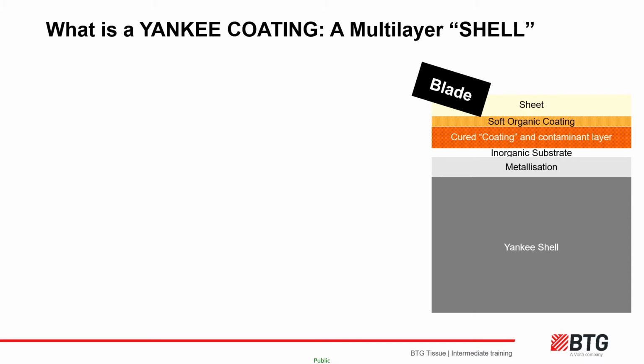If we could take a cross section through what would be an ideal Yankee coating, these are the layers we would want to see. On top of the Yankee shell and any metallization layer would be an inorganic substrate made up of minerals and salts, either naturally there from the spray or process water source. These would be calcium carbonate, iron and magnesium salts. They could also be deliberately placed there, for example by phosphate addition, and by the ion complexes it forms with the surface of the Yankee, or the metallization.